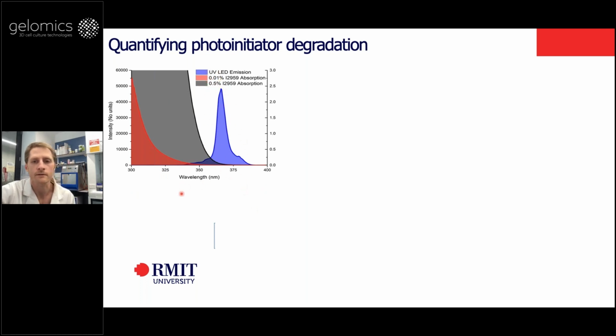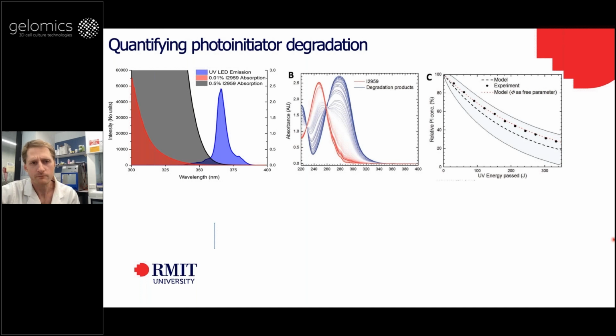It's centered on 365, and then this gray band and the red one show the absorption spectrum of the photoinitiator that we're using, which in this case was I2959, this being our first piece of work. And what's important is actually the overlap between these two curves. That can tell you how much light energy is actually being absorbed by that solution, and that's important for characterizing some other properties, which I'll talk about in a minute.